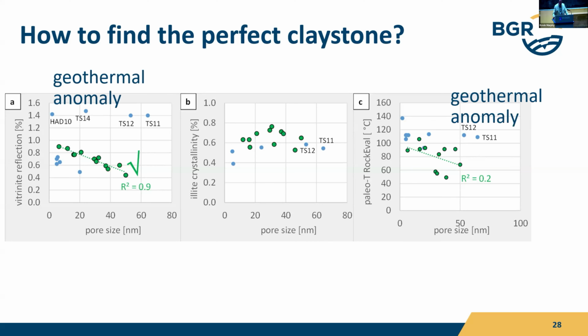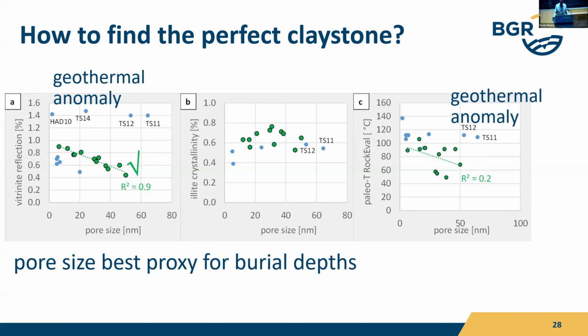In case of illite crystallinity and pore size, there was not a nice correlation. And in case of the pore size against Rock-Eval, we could more or less confirm the results from figure 8 and the fact that the samples from the geothermal anomaly plot out of the trend. That means, and that is probably one of the most interesting conclusions of the study, the pore size seems to be the best proxy for burial depth, because it's not affected by cementation, it's not affected by geothermal anomaly, it's mostly affected simply by the load you had above the material.